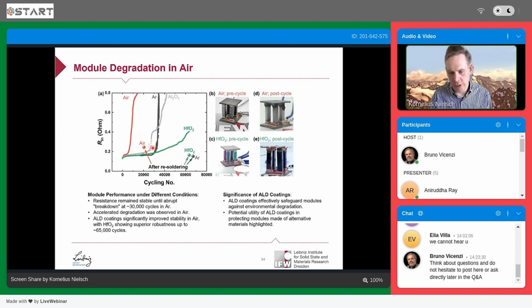One of the main arguments why hafnium oxide behaves much better is that we don't have any solid state reaction between magnesium or magnesium oxide and the hafnium oxide. Whereas with aluminum oxide, some solid state chemical exchange reactions happen with the magnesium oxide, and this makes the module overall less stable.